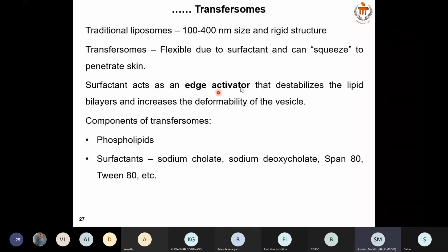Edge activator is nothing but the surfactant which we use here. As I previously told, non-ionic surfactants we generally don't use, for example, tweens or spans, because usually with the phospholipids which are used here, there will be leakage when we use non-ionic surface active agents, that we have observed in the lab. Generally used edge activator is sodium deoxycholate.